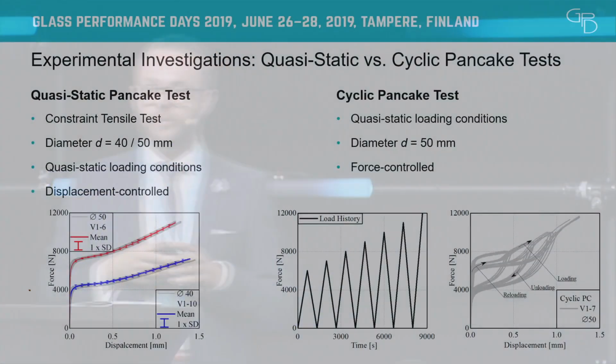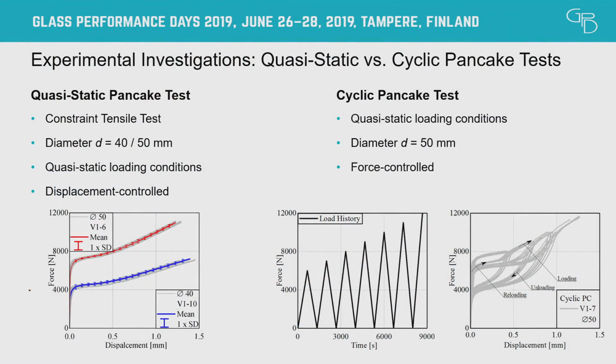we can see, let's say, recovering of our stiffness. And this is an effect that was never observed in a material. I'm not familiar with this effect. And we say, okay, if we have this reloading, we do not have the same stiffness as for the unloading. We have a healing effect. And this is what we can see in these crazy experimental testing curves. Yeah, we performed, I think, 7 tests. And what you can see here, the curves are pretty similar.